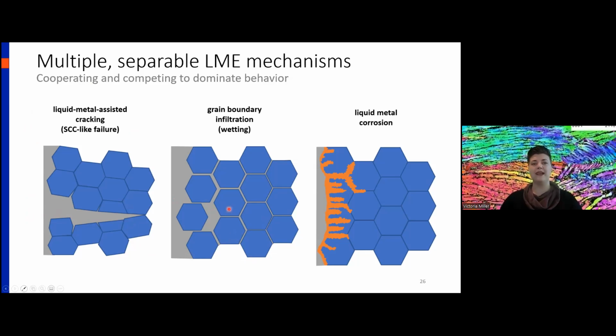So your liquid wicks along the grain boundaries, and then because you now have a liquid at your grain boundaries, your material no longer has any mechanical strength because you can't apply tension to a liquid. And then the third class of mechanisms is liquid metal corrosion. And this could be selective leaching from the alloy, or this could be formation of a corrosion product either within the grains or within the grain boundaries. And I'll show you a little bit more information on what each of these proposed mechanisms looks like.